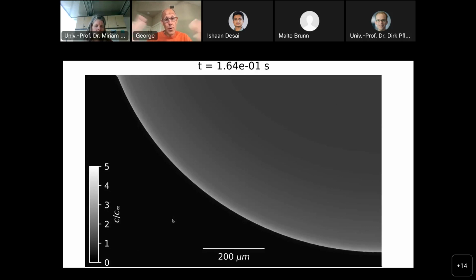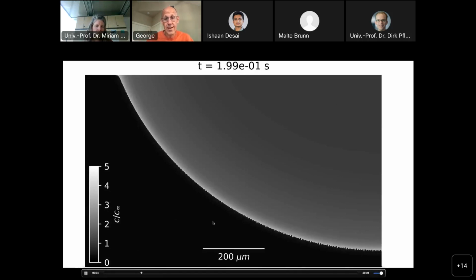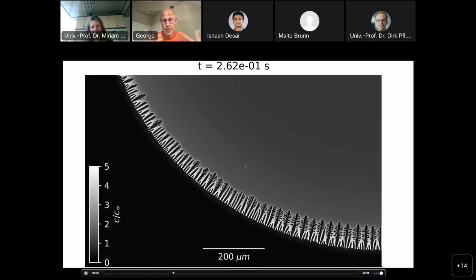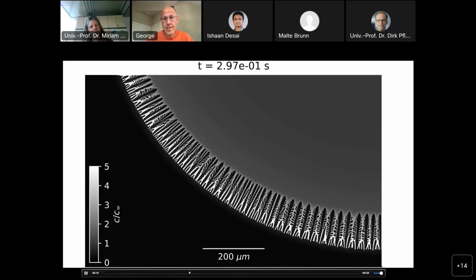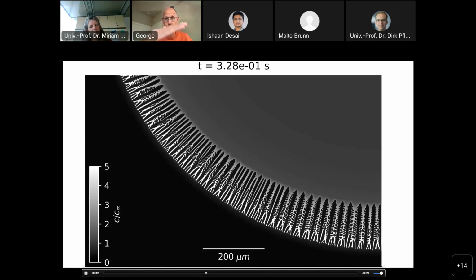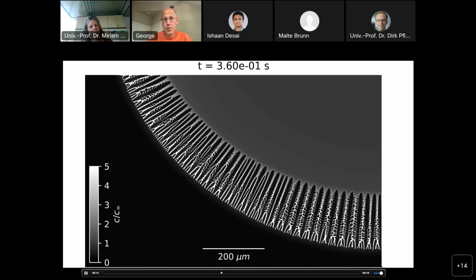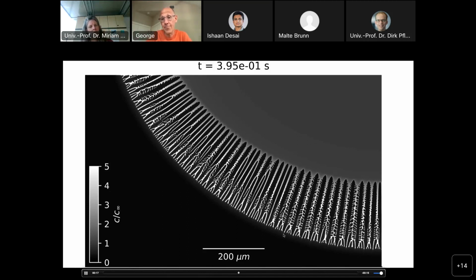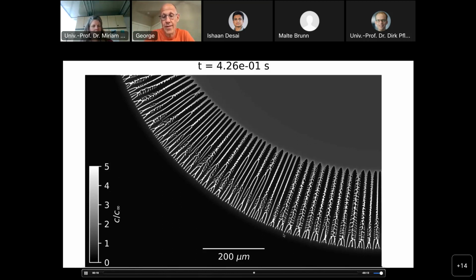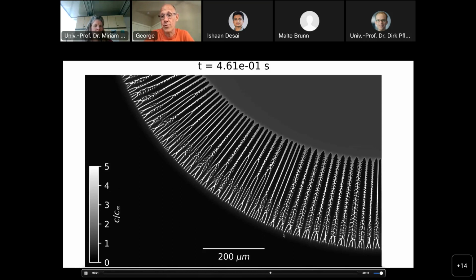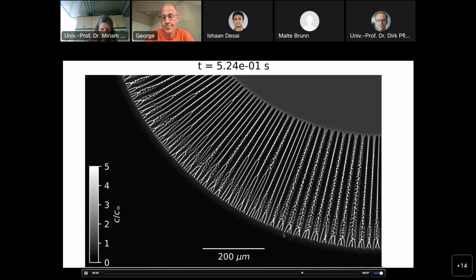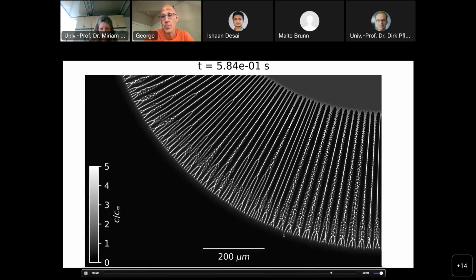So here we already have the heat profile. We have solved the heat transfer, and given the heat profile, the material slowly cools as we go in this direction. It solidifies, and you can see the solution of a partial differential equation, a phase field, that captures this microstructure formation. And that's the simulation, and that's what we try to capture.